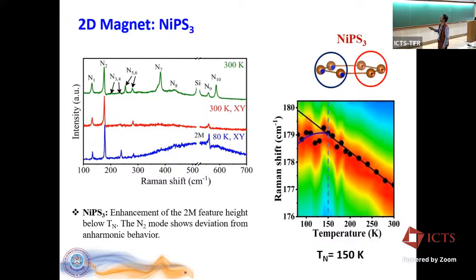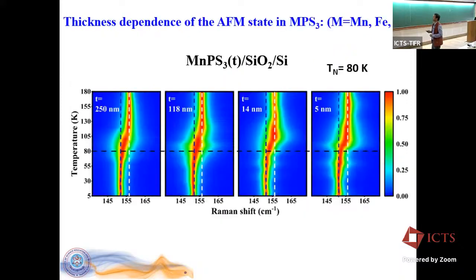So if we plot the phonon modes, for example, here we're plotting this N2. Now you see this straight line is basically the behavior of the anharmonic trend, if I may remind you. So this is that anharmonic trend, and there is a deviation which is happening right around 150 K, which is the antiferromagnetic ordering temperature. So this becomes our indicator of the magnetic ordering. So we will now look at what happens if we thin down. Okay, it's not something we're doing for the first time. We're basically establishing it again.